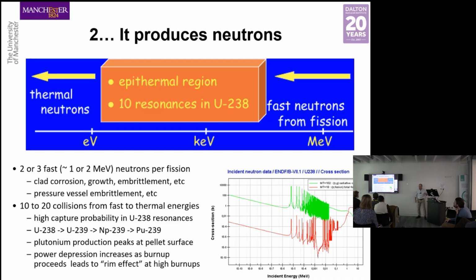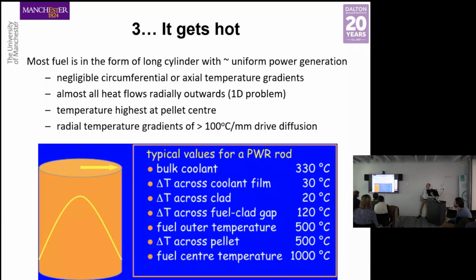It produces neutrons, of course, fine. It gets hot. Yeah, it gets really hot. If it's UO2, the center temperature of typical light water reactor fuel will be about 1,000 degrees C, give or take 100 degrees C or so. The temperature on the outside, the coolant temperature, is just over 300, about 330. So a very significant temperature gradient across a fairly small distance.